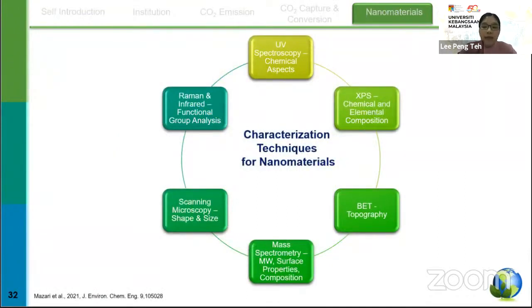In material science, characterization is very important. In order to synthesize very novel and functional nanomaterials, we need to characterize them with various types of characterization techniques. I listed a few, but not limited to this slide. We have UV spectroscopy for the chemical aspect. We have X-ray photoelectron spectroscopy, XPS, for chemical and elemental composition. We have BET, nitrogen physisorption, for topography, basically about porosity, the surface area, pore size, pore volume. And we have also mass spectrometry, which determines the molecular weight, surface properties, and also composition. We have microscopic techniques like SEM, FESEM, TEM, basically for the morphology of the particles, their shape and also size. And we have also Raman and infrared for functional group analysis.